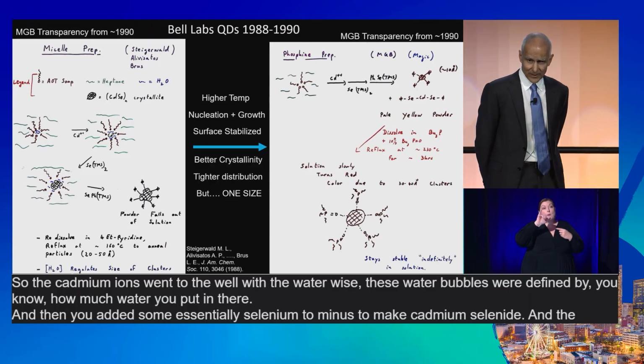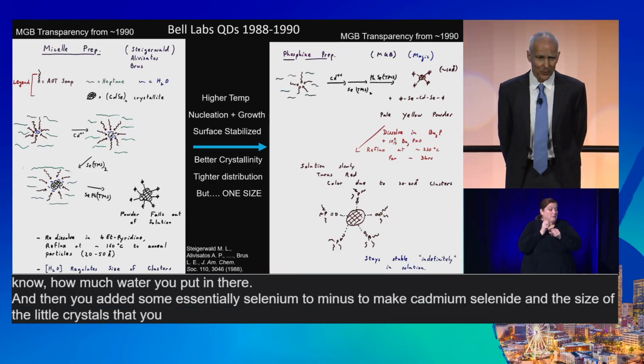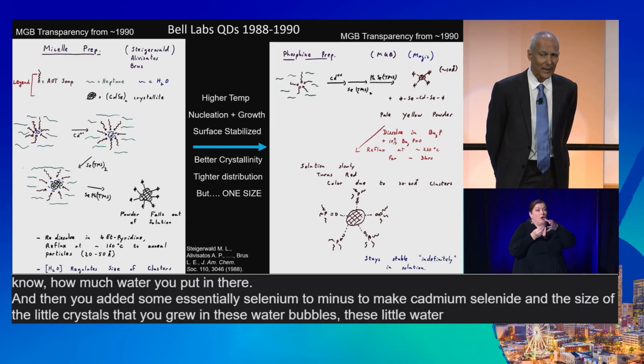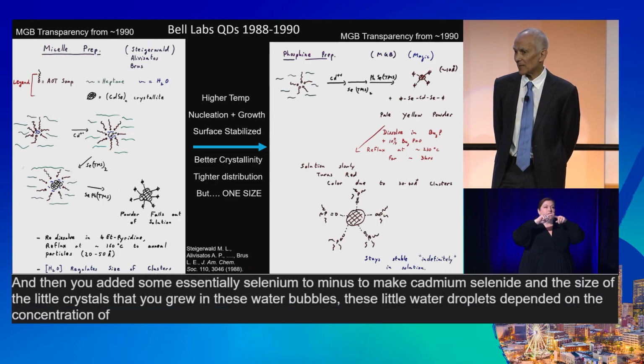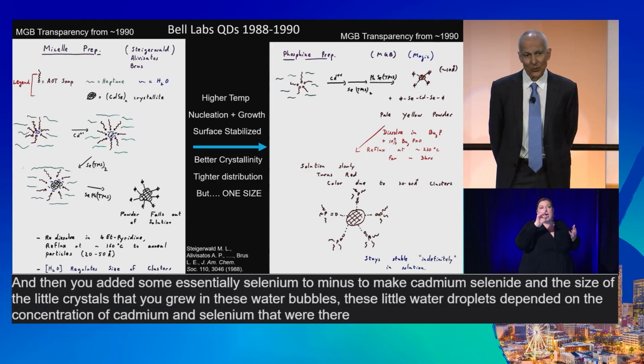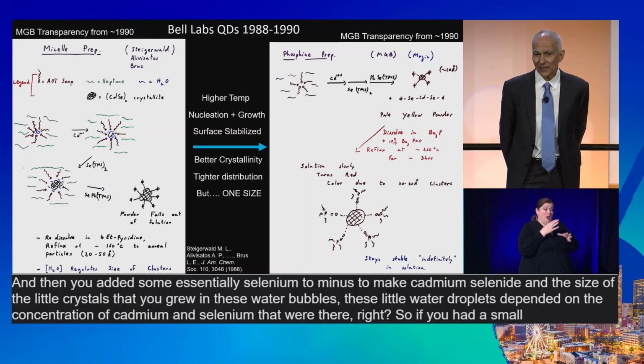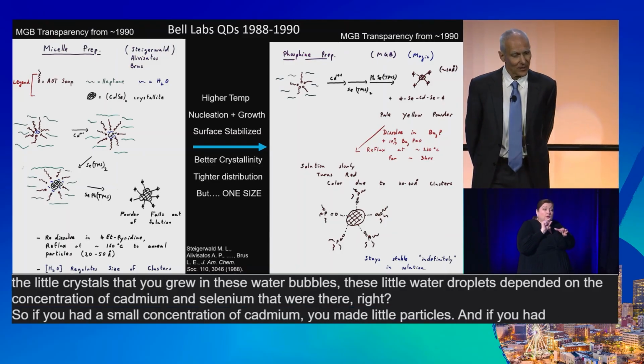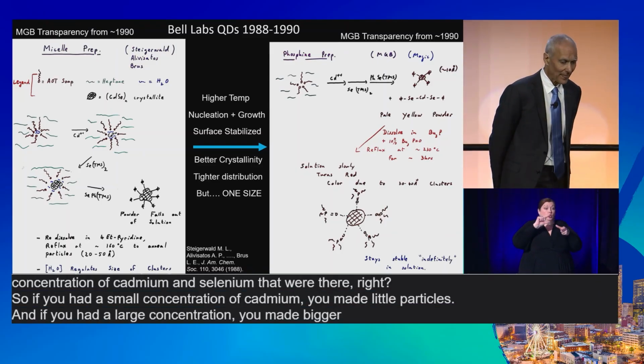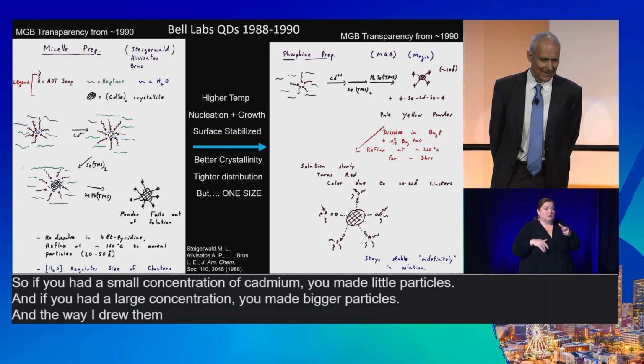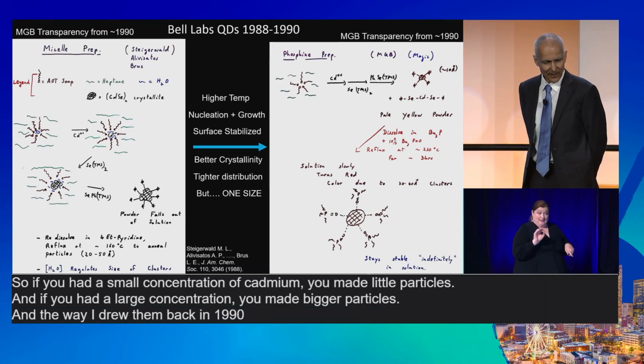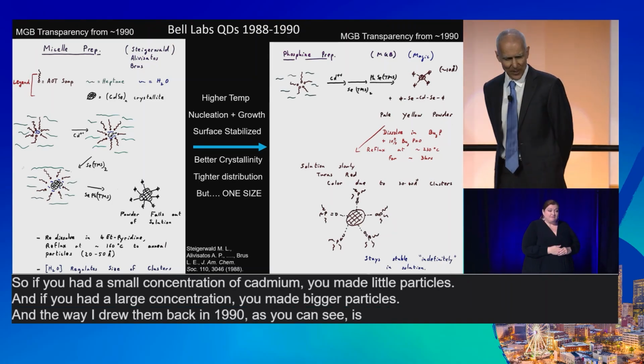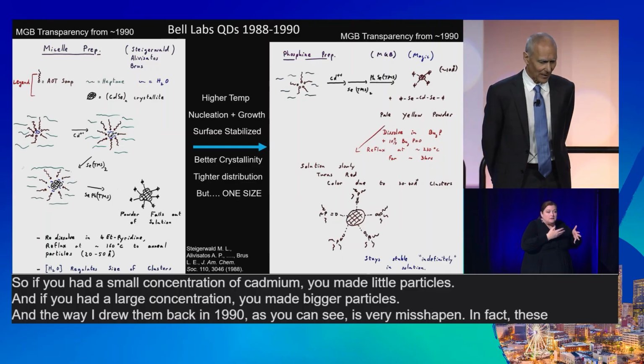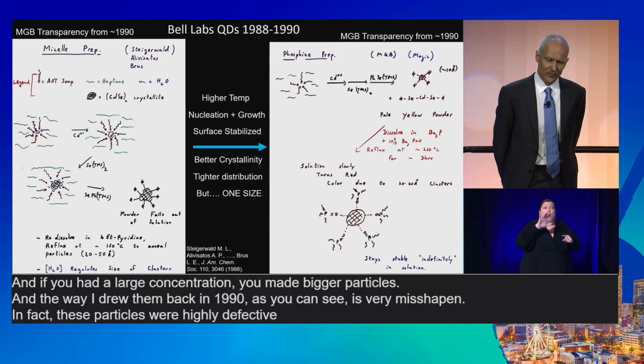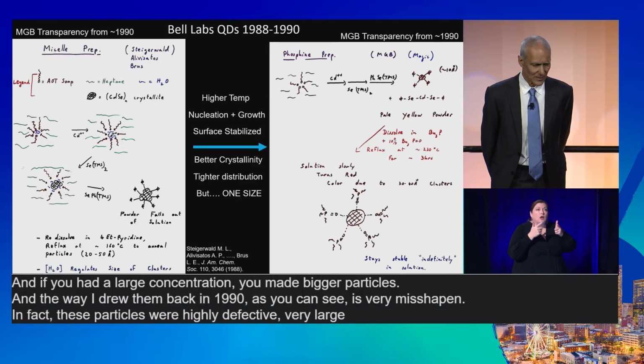And the size of the little crystals that you grew in these little water droplets depended on the concentration of cadmium and selenium that were there, right? So if you had a small concentration of cadmium, you made little particles. And if you had a large concentration, you made bigger particles. And the way I drew them back in 1990, as you can see, is very misshapen. In fact, these particles were highly defective, with very large size distributions.